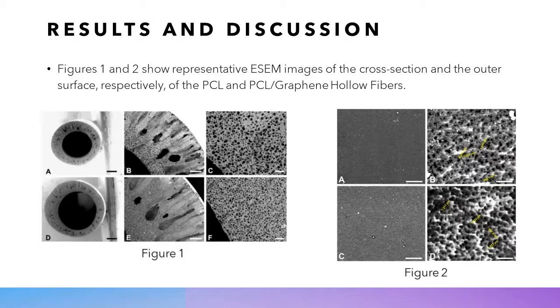Results and discussion. Figures 1 and 2 show representative ESEM images of the cross-section and the outer surface respectively of the PCL and PCL graphene hollow fibers. In Figure 1, cross-section ESEM images of PCL and PCL graphene hollow fibers were employed to determine the hollow fibers' morphological characteristics, as shown in the picture. Next is Figure 2. In Figure 2, outer surface ESEM images of the PCL and PCL graphene hollow fibers show the higher magnification details of the external surface of PCL and PCL graphene hollow fibers.